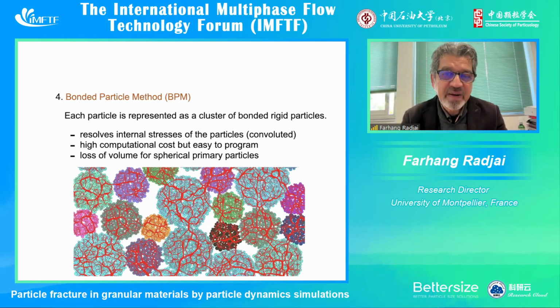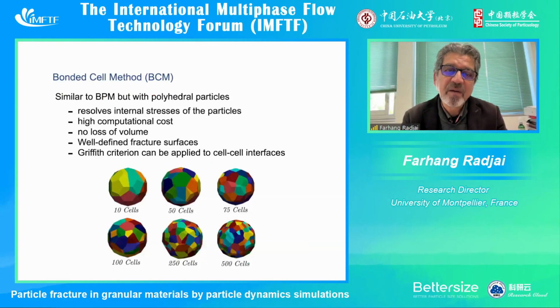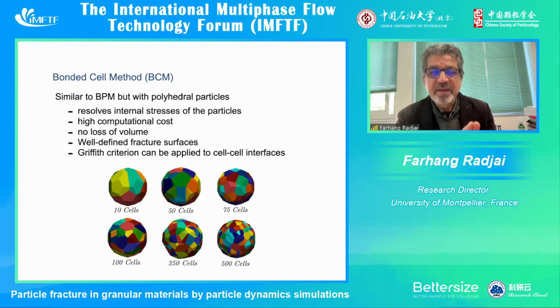in which we don't use spherical particles as in the bonded particle method, but polyhedra. I think now there are many more people who are trying to use this method in which we tessellate each particle into polyhedral particles as disordered as possible. I mean, it should not be regular, but we can add some texture even when we tessellate. It resolves the internal stresses of the particles. Of course, we have to include the material behavior through the interface between the polyhedra inside each particle.